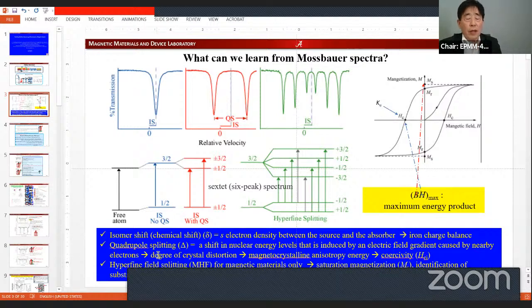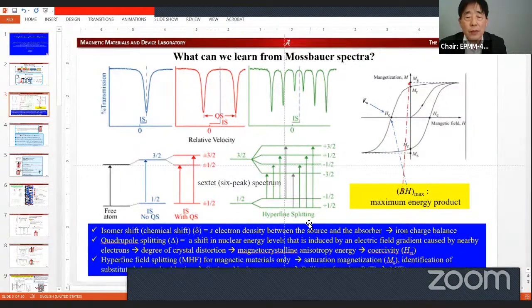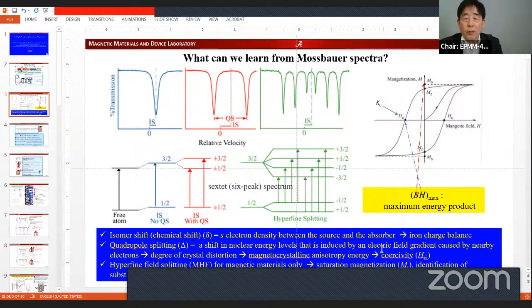Let's go back to the isomer shift, otherwise named chemical shift delta. That is the s electron density difference between the source, meaning the gamma ray source right here, and the absorber, in this case the barium ferrite sample here. Once you measure the isomer shift, you can get the iron charge balance, +2, +3, whatever. And then the two-line spectrum, that is the QS, quadrupole splitting. Quadrupole splitting is a shift in nuclear energy levels induced by an electric field gradient caused by nearby electrons. That means we can have information on the degree of crystal distortion. Crystal distortion relates to the magnetic anisotropy energy. Once you have the magnetic anisotropy energy information, you can predict the coercivity as measured by the magnetometer.